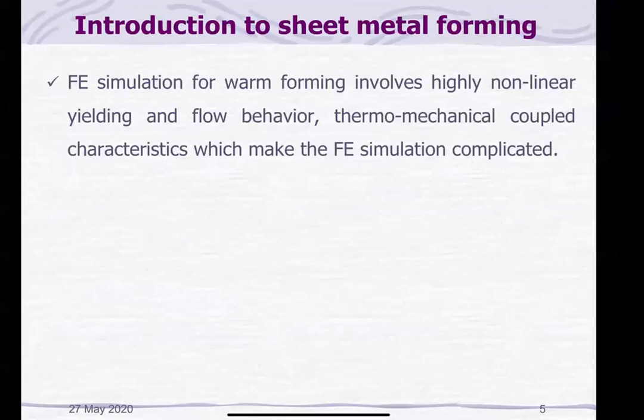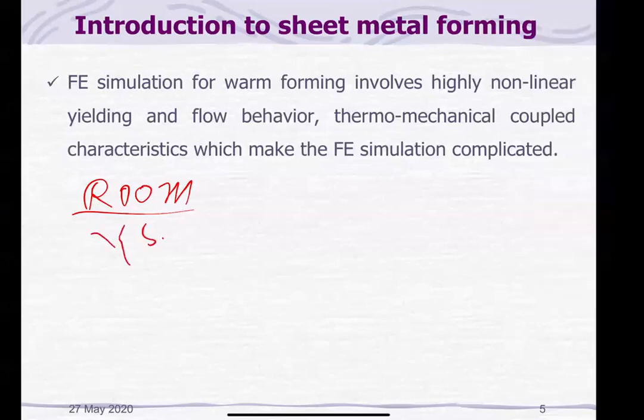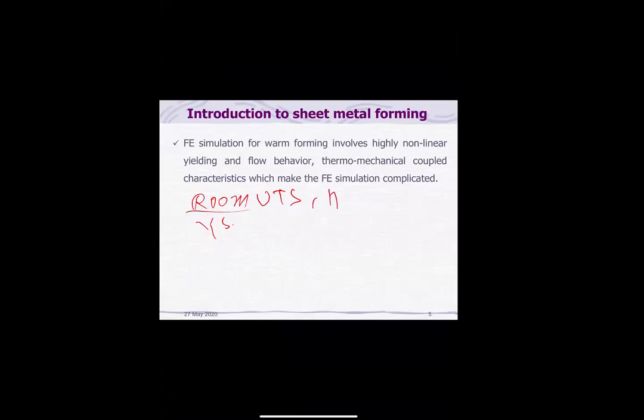Then finite element simulations of warm forming involve highly nonlinear yielding and flow behavior. What is the problem? When you are forming the material at room temperature, the number of parameters in evaluating it are quite limited. For example, when you are thinking of room temperature, what are the parameters that you have to give to any simulation? Yield strength, and then ultimate tensile strength, work hardening exponent and strength coefficient K, and then Lankford parameters like R0, R45, R90. And Nitin was also telling that biaxial parameters are also used for simulation for some special materials. But these parameters are the minimum.